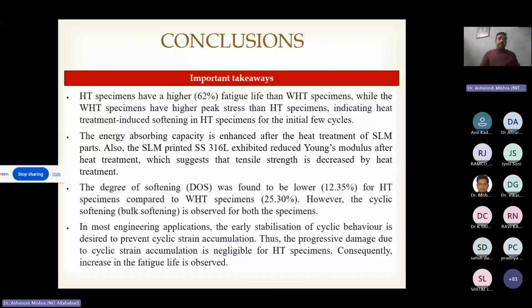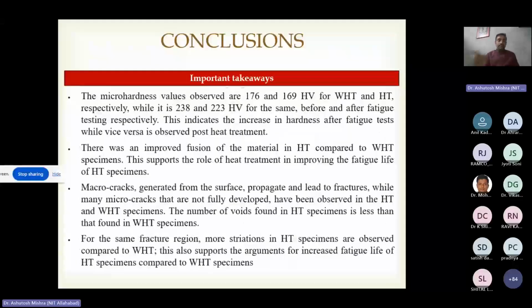Why such a thing is happening is again a part of the study carried out here. Then the degree of softening was found to be lower for the HT specimen compared to the WHT specimen, which exhibited around 25.3% degree of softening. In most engineering applications, early stabilization of cyclic behavior is desired to prevent cyclic strain accumulation. Thus, the progressive damage due to cyclic strain is negligible for the HT specimen. Progressive damage means, again, ratcheting. Consequently, an increase in fatigue life is observed. So, very little ratcheting is seen in the HT specimen.